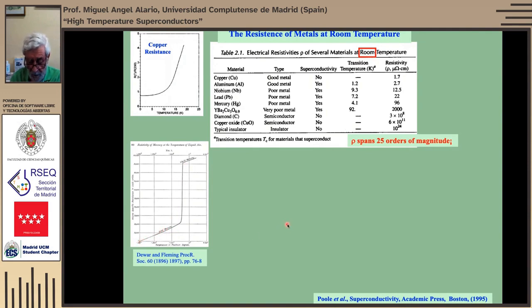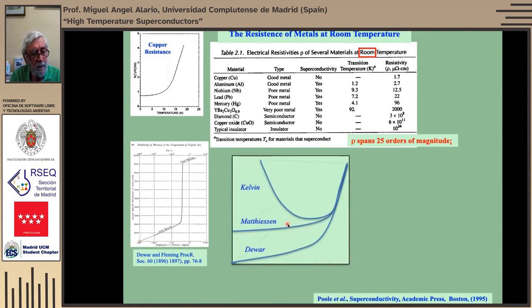He saw that if he could cool down, that would go down to zero. So at the time, there were, in fact, three models of the evolution of the resistivity of a metal as a function of temperature. It was the model of Dewar that we have just mentioned. The model of Kelvin. Kelvin thought that actually the electrons would stop moving when you cool, and then the resistivity will increase. And then there was the model of Mathiesen, who is not so well known, certainly not in the general public, but he is in physics, and he thought that the resistivity will attain a fixed value, which will depend on the purity of the material.